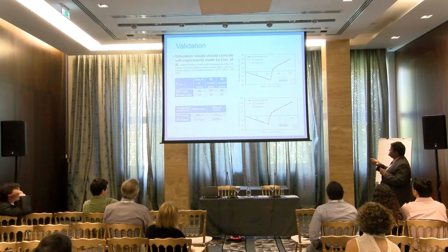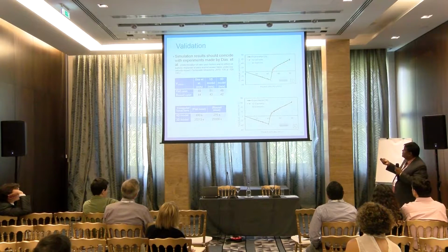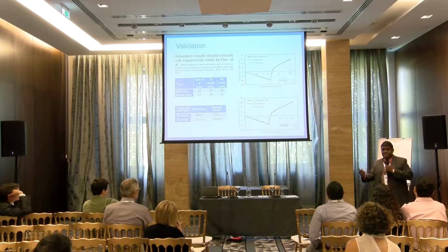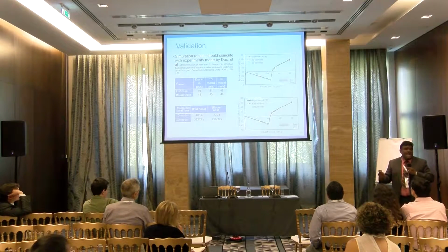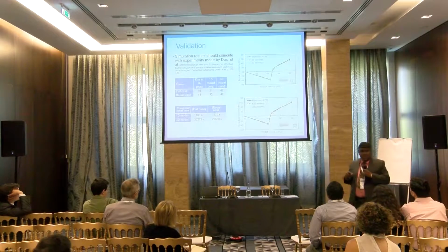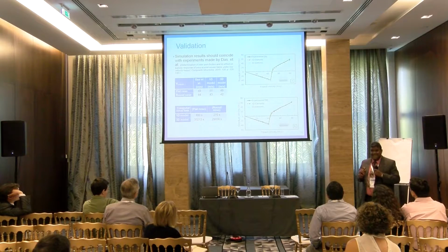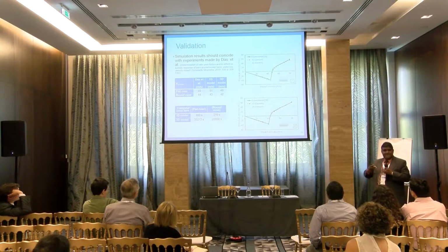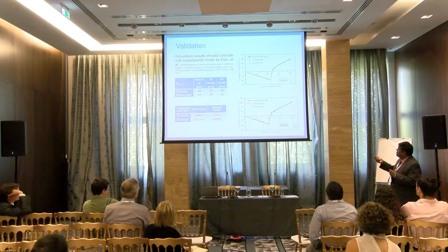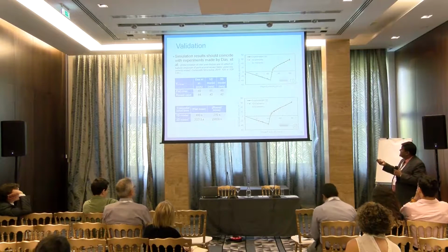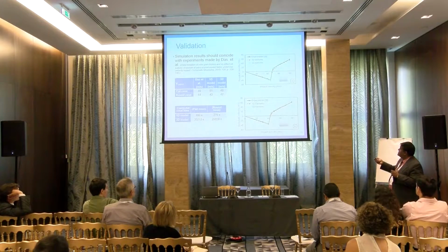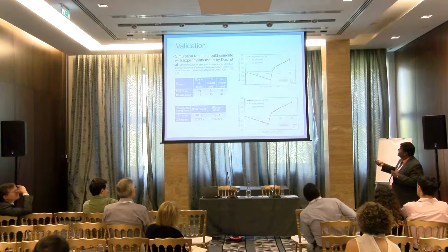Then we move on and reach a stage where the projectile starts penetrating the fabric, so there will be significant damage. We can see the residual velocity increases significantly over a short linear distance. Then this point is where the projectile just penetrates, just comes out the other side, but doesn't have any velocity. This is what we call the limiting velocity or critical velocity, which we denote by V0. Note, we are not using V50, if you are familiar with the V50 limit for impact. We are using the V0 limit, which is just the velocity needed to penetrate the fabric. So this is our V0 point where, for a given impact velocity, in this case about 50 meters per second, the projectile just penetrates the fabric. We compared these for two cases, impact velocity versus residual velocity, for both flat nose and round nose.